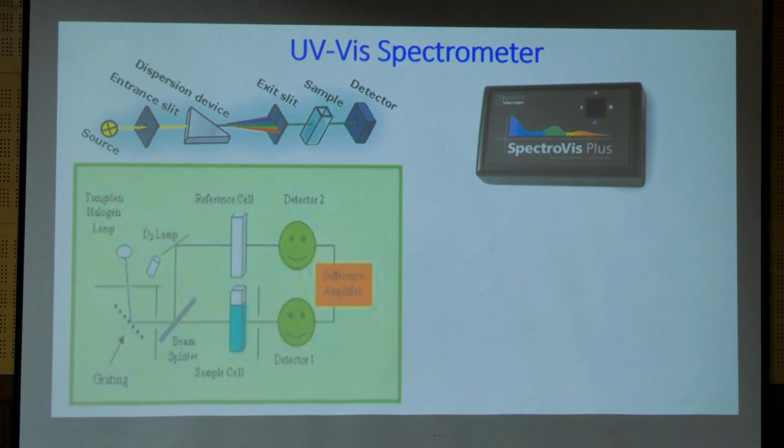It's a combination of both which is detected here. So what you have to do is put a blank, first record the spectrum, take the data, then put a sample with the nanoparticles, again take the spectrum, overlap, remove, and do certain calculations to arrive at the absorption of the particles only.